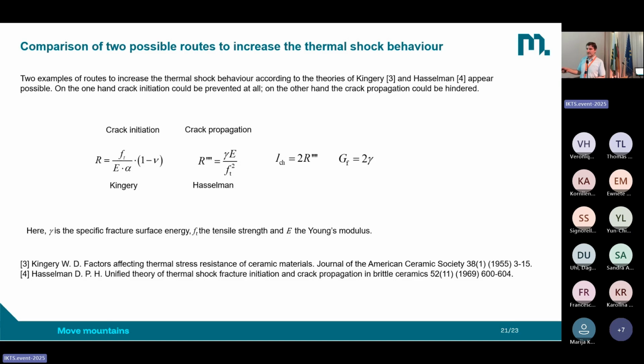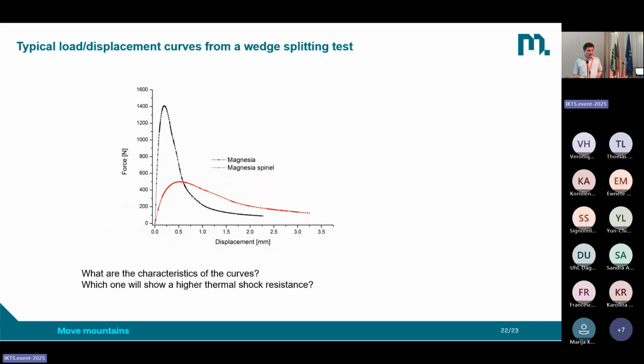Because in case of Hasselmann, you can have initiated cracks, and he would like to avoid that these cracks already there do not grow. So he uses the resistance of the crack to propagate. So these are the ideas, and what is now relevant for the refractories? If we look here again on our diagram, then we see maximum force is much higher for the black curve, for the magnesia refractory, and the maximum is lower for the magnesia spinel refractory. So on the first glance, people might say, okay, I expect a higher thermal shock resistance for the magnesia refractory because we have a higher maximum force.